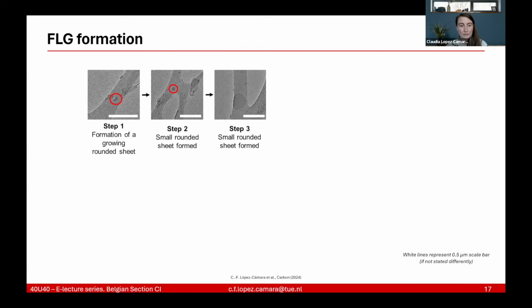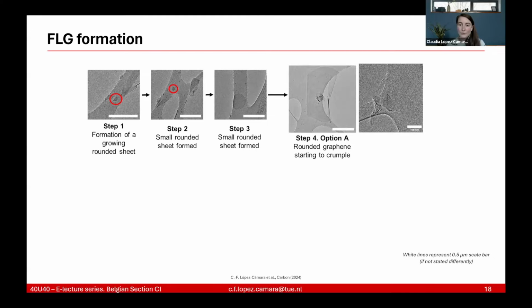So step one would be the formation of the growing rounded sheet of graphene, single layer. Then the small rounded sheet was formed in step 2. And in step 3, this small rounded sheet was formed and was also growing. And eventually this growth, as you can see in this video, as well as in the picture, because the graphene was growing so much and it was just one layer of graphene, it was mechanically unstable and was self-folding or crumpling in a random way.